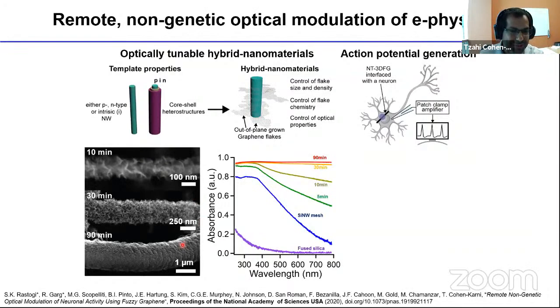Something really unique about these materials is that they are kind of the opposite of graphene. Graphene should be 97.4, if I'm not wrong, or 97.6 percent transmittance. In our case, it's 97% absorbance. A mesh that is composed of these wires will have close to 97% absorbance. So it's basically a black material, not super black like a vertically oriented carbon nanotube array, but it is a broadband and a very efficient absorber.